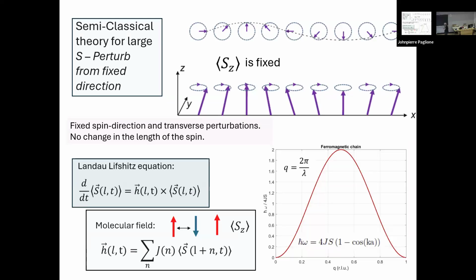Okay, now onto the main point of this talk. I pointed out that neutrons are sensitive to the magnetic moment of a material. And if you want to characterize the magnetic interactions in a material, one way to do it is to measure normal modes. Now, that shouldn't be a big surprise, because if you think about a spring attached to a big mass like a wall or something, with a particular spring constant, that's going to have a characteristic frequency that goes as the square root of k over m. So if you can measure that characteristic frequency, you can understand the interactions.